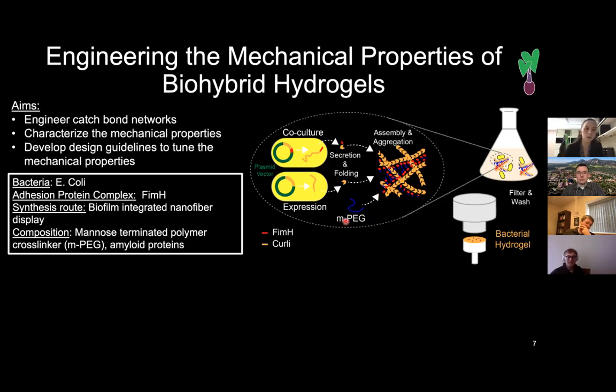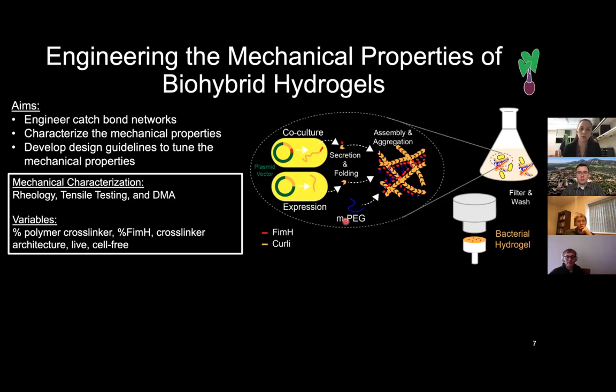So then, can we characterize these mechanical properties, which we'll do through rheology, potentially tensile testing and DMA, where we can get interesting rate effects. And we can change the cross-linking percentage in our bath, where we'll take these and grow them in this liquid culture, and then we can filter them out and create these bacterial hydrogels. And then change the percentage of these FimH or these catch bonds in these systems, which we can do by co-culturing one without those and one with those. So it'd be a random copolymer essentially. And then we can look at these in terms of live or cell-free, where we can wash out the cells in these systems and then look at these mechanics.